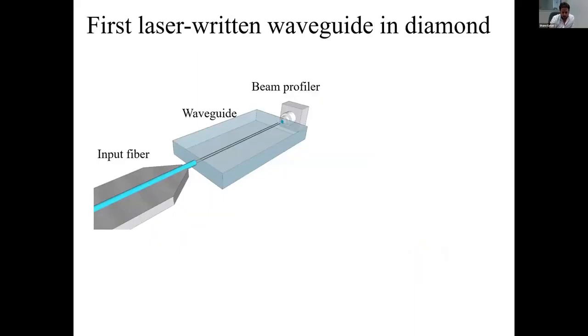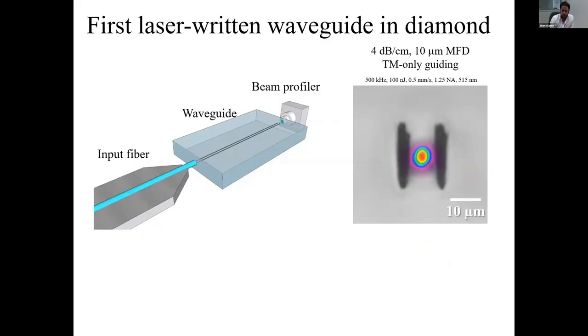Our group was actually the first to demonstrate a laser-written waveguide in diamond. Essentially, as I mentioned, we wrote these two damage lines in very close proximity. This shows a microscope image with an overlaid mode profile. Essentially, the laser came in from the top to form this elliptical damage line, and then we formed a second one adjacent to it, roughly 10 microns away. Of course, the sample was scanned out of the page to form this line throughout the sample.